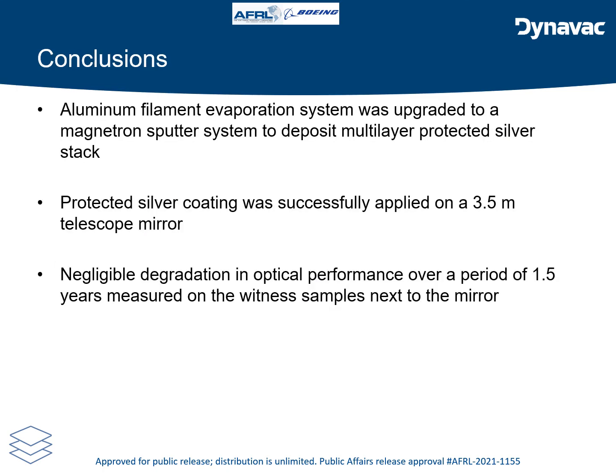Conclusions. An aluminum filament evaporation system was upgraded to a sputter deposition system to deposit a multi-layer silver stack. A protected silver coating was successfully applied onto a 3.5-meter telescope mirror. Negligible degradation in optical performance was observed over a period of 18 months on the witness samples placed next to the mirror in the telescope.